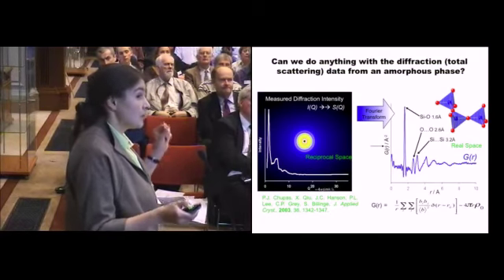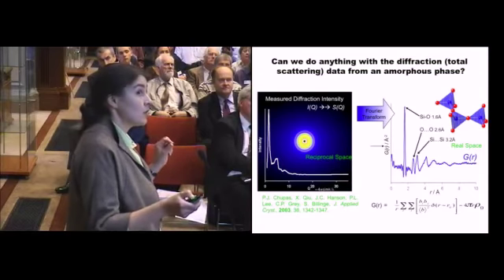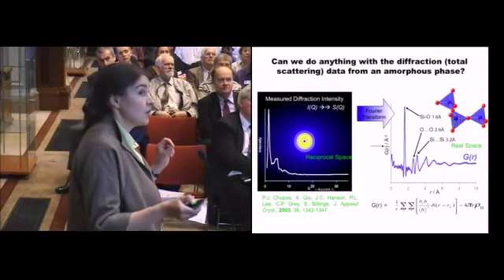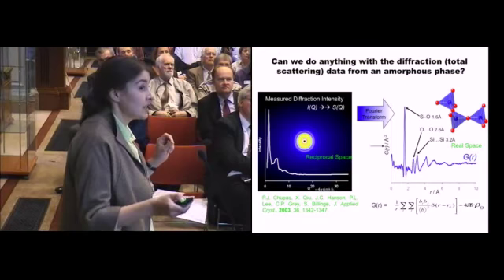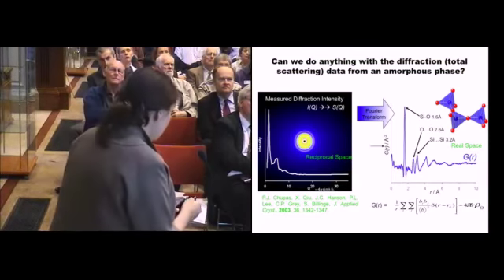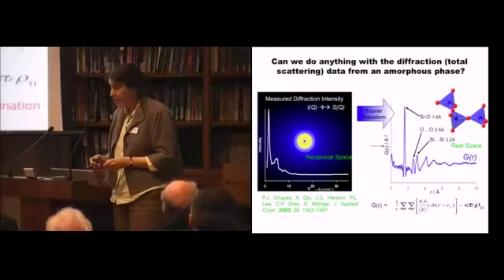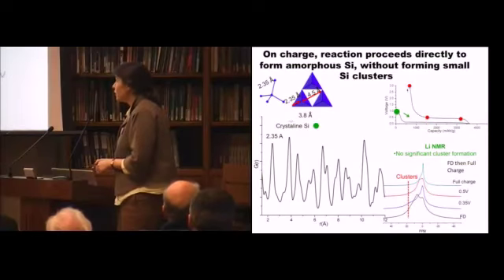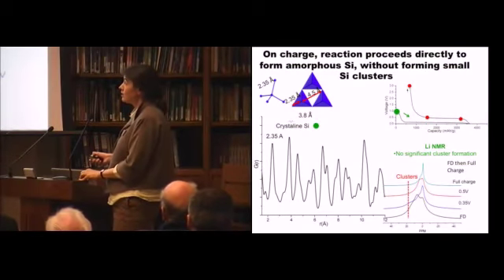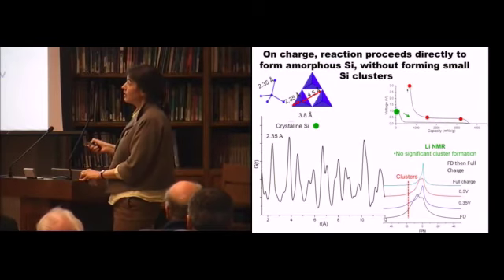So the first peak is the shortest distance, so the silicon-oxygen peaks, then comes the oxygen-oxygens, and then come the silicon-silicons. And the intensity of these peaks tells you how many of these environments you have in the solid. So you can go from your crystalline silicon structure with the silicon-silicon peaks in the first coordination shell, the silicon-silicons of the tetrahedra, and the silicon-silicon peaks across the tetrahedra.